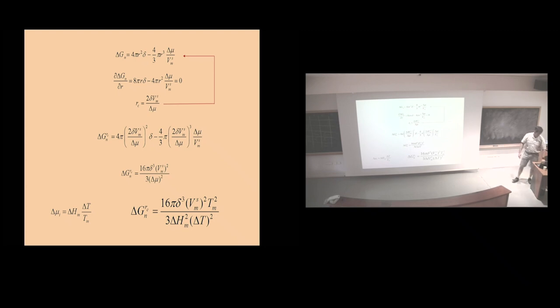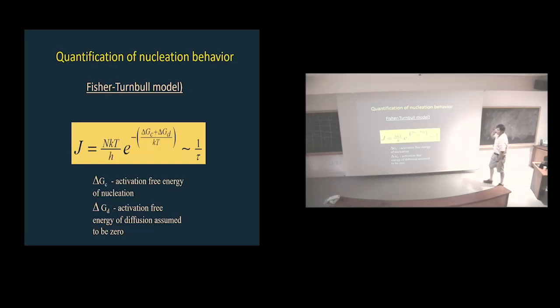And so we understand nucleation from the Fischer-Turnbull model, in which our rate of nucleation is your NkT over h. But look at this exponential term here. The classic view is that you have a free energy of nucleation, of crystallization, and one of diffusion. And most people, and this is another one where I'm going to be yelled at, assume the free energy of diffusion is 0, because it's too hard to get. And so you're like, get it?